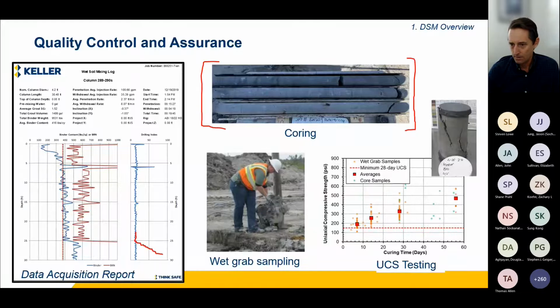We take wet grab samples. Here's a field engineer taking a wet grab sample out of a trapdoor bucket that we push down into the soilcrete column, grab the sample, and then we cast it into cylinders, typically 3 by 6 inch cylinders, and then break them at different curing times. And you see there is a strength gain with time with soilcrete, just like there is with concrete. And we typically target the 28-day strength as our specification compliance strength, but we monitor the strengths to make sure we're on track to get to that 28-day strength during construction. We also will break specimens from the cores themselves, and typically the data is more or less consistent between the grab samples and the cores.